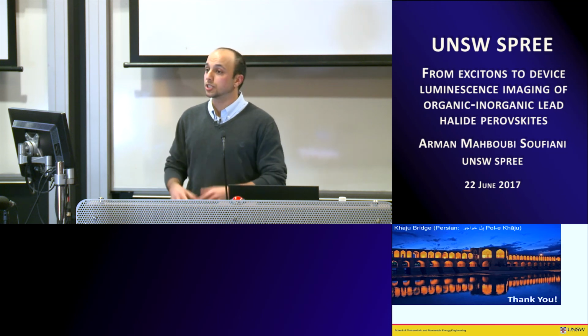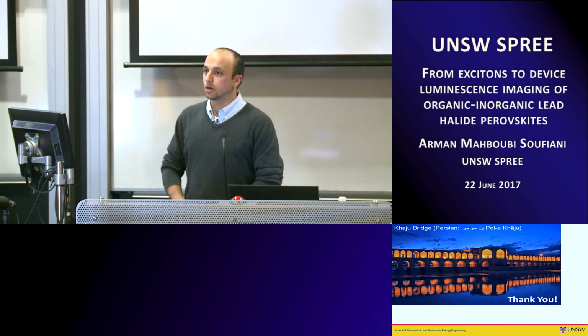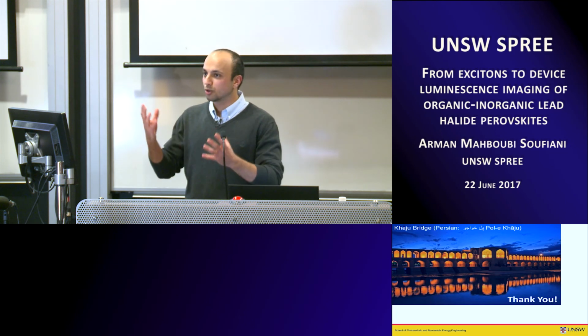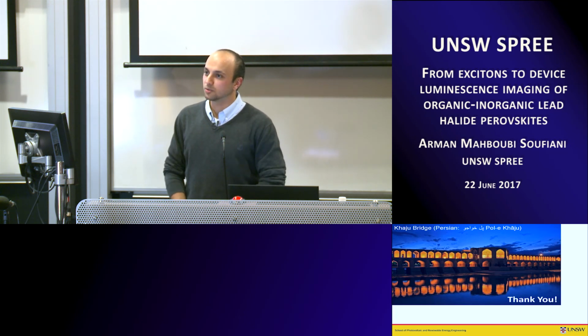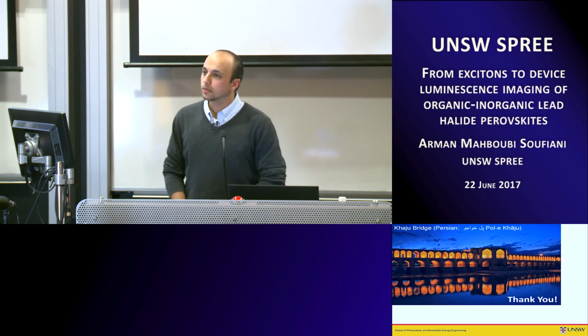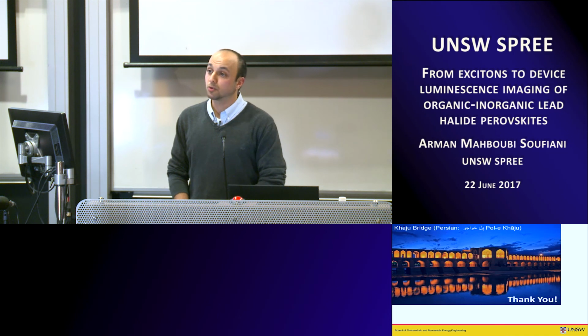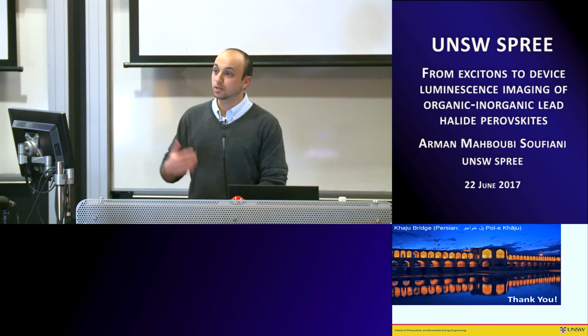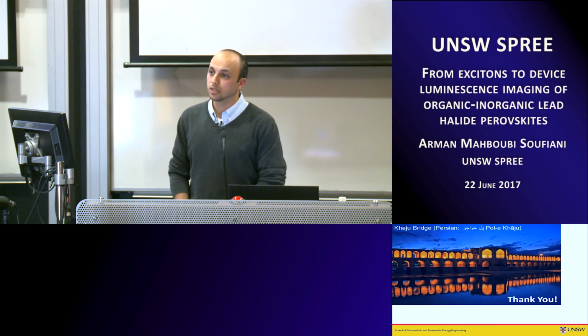And also the composition. So this study was done on the archetypical perovskite composition, which is methylammonium lead iodide. If you make different compositions with different cations and halides, you get more stable devices. And currently, 1-year stable devices have been reported in perovskite by incorporating some 2D perovskites into the 3D perovskite.